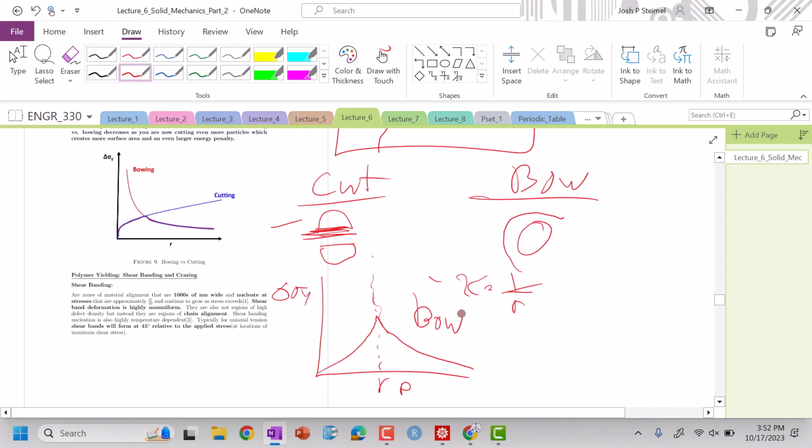Why? Well, if I have a very, very large particle, then my curvature is very, very low. So I'm not creating much curvature. Again, the Earth is huge. It has a large radius. It is not flat. I want to emphasize that. I don't want to get this video taken down. It has curvature, but it's very, very low. So for large particles, there's a low penalty to bow around them. Now, for small particles, this curvature penalty will increase significantly. And if I have small particles, I could cut those because I'm not creating much surface area, so I'm going to cut here. So that's the distinction.